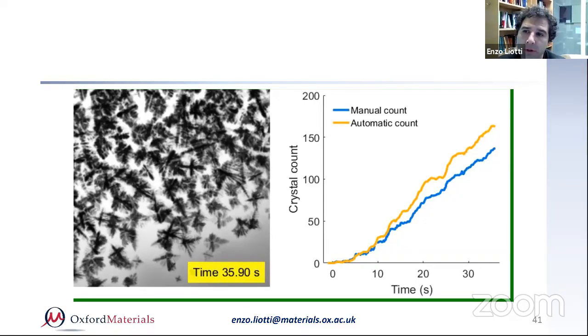So I'll give you an example. If you want to image a phase transformation where a phase is just changing crystal structure, but not much composition, then the kind of setup we use won't distinguish it. But you could use diffraction, another type of setup that will give you that kind of information. Or you can use a detector that gives you the composition of a multi-elemental material, right? So you could map more than one element. For convenience, we use binary alloys because they are easy to study and you can learn the science behind it. But nobody stops you from looking at a ternary alloy or a different problem.